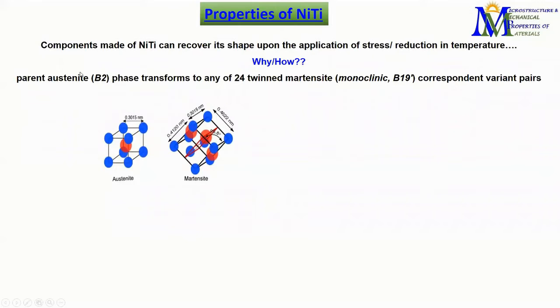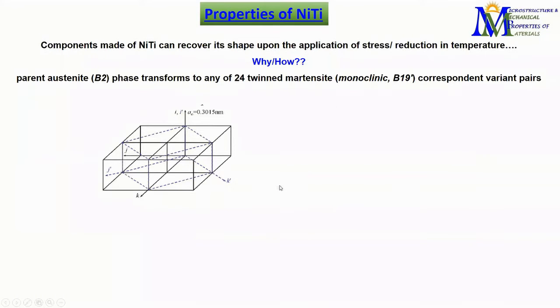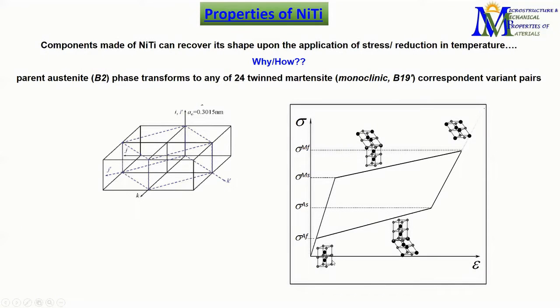As I said, nickel titanium can recover its shape by the application of stress or the reduction in temperature, or both. This is possible because of the conversion of the austenite phase to martensite, through the correspondent variant pairs. I'm just going to explain that in detail. And this is reflected in its stress strain behavior accordingly. Initially, let's say we have the austenite phase, which is a cubic structure, a BCC B2 structure, where the nickel atoms are at the corners and the titanium is at the body center, and vice versa in the adjacent crystal lattice. So this is what it is in 2D.